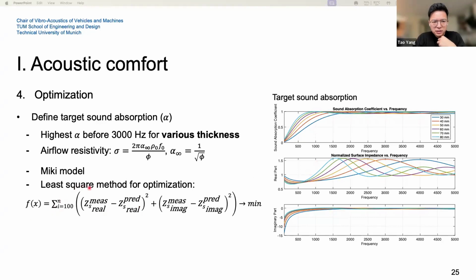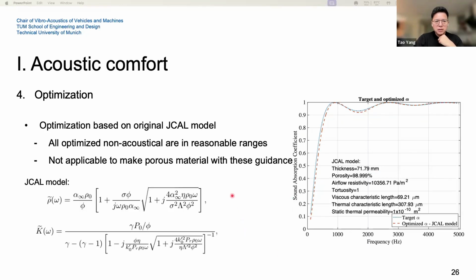Then I use the least square method to find the minimum value of this function to get the closest curves on the normalized surface impedance. In this function, I need to calculate the minimum value of the real part and also the imaginary part of the normalized surface impedance, and then get the minimum value by the Levenberg-Marquardt algorithm. Usually, if we use the original JCAL model to do optimization, it's possible, and all the results of the non-acoustic parameters we achieved here are in a reasonable range.